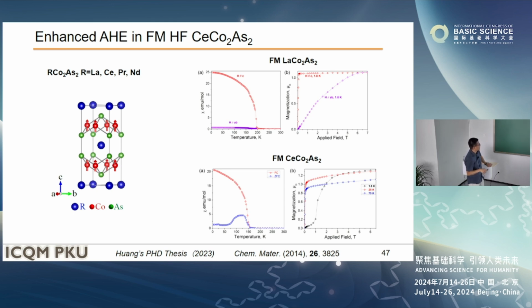Some papers haven't been published, but are posted on arXiv. This compound is a cerium-based compound with cobalt, in the 1-2-2 structure, like the iron-based superconductors. The only difference is the cobalt has a net magnetic moment, meaning it has itinerant ferromagnetism, and its TC is around 200 Kelvin. The lanthanum has no 4f electrons. You see, the magnetism is purely from the cobalt.